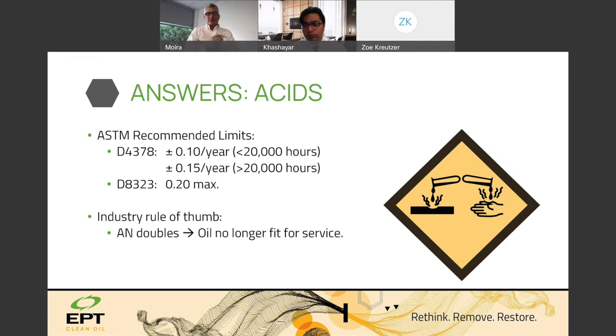ASTM says that acid numbers should be increasing by less than 0.10 in 20,000 hours and up to 0.15 when you're above 20,000 hours per year, okay? I would say that the modern lubricants are even more stable than this, okay? I've seen customers run baseload turbine applications for 10 years and still have an acid number of 0.05. So if you're having a hard time controlling your acid number, you know, please reach out. We might be able to offer you some advice in that regard.